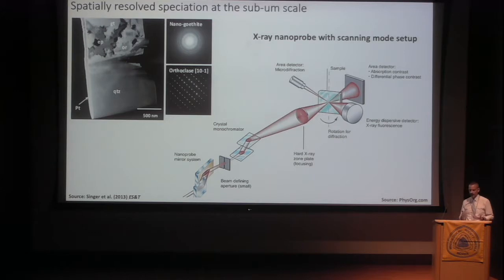But we have, as Mike just showed, a very high degree of ability to characterize these nano phases, these sub-micrometer phases. And this is a focused ion beam TEM section showing that interface between the primary grain, in this case quartz, and then the secondary mineral surface coating above it, which is a complex mixture of mineral phases and nanomineral phases. And we have, through electron microscopy, the ability to define this physically and chemically complex environment,